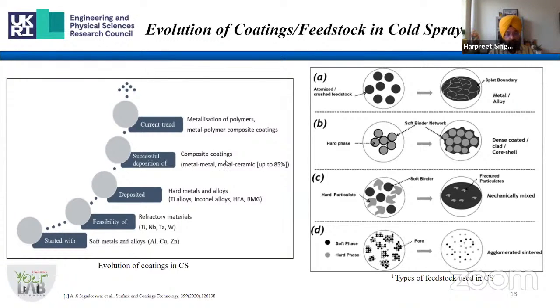And then we have composite coatings. Again, a very important contribution by cold spray. This is like metal or metal ceramic coatings. They can be produced with even up to 85% ceramic content.